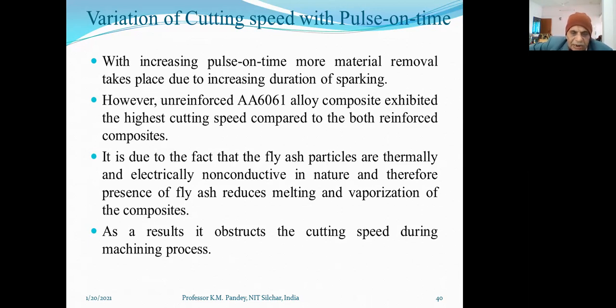It is due to the fact that the fly ash particles are thermally and electrically non-conductive in nature, and therefore the presence of fly ash reduces melting and vaporization of the composites. As a result, it obstructs the cutting speed during the machining process.